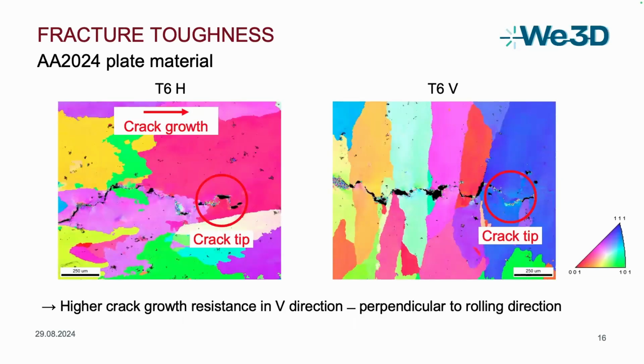In the EBSD mapping, we can see that it seems quite easy for the crack to propagate along the grain boundaries here in the horizontal specimens. Sometimes the crack also has to go across the grains, but in the vertical orientations, it's quite hard for the crack to propagate through all these grains, and therefore the resistance against cracking is higher here for the vertical samples.